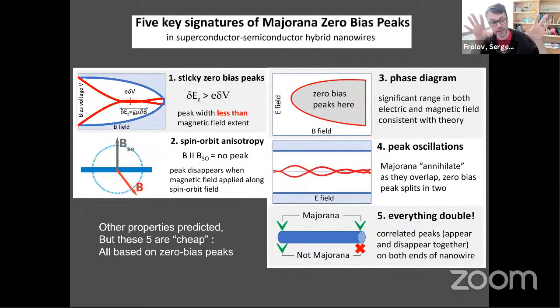So I put together this list of 5 properties, 5 criteria. If you satisfy all 5, there is a great chance you have found Majorana modes in your experiment. And if you're not working with nanowires, but with a different system, there will be your own set of 5, maybe slightly modified, but with some overlap with my list, right? But I showed you that if you look at part of the data, you can fine tune it to look like Majorana, right? So you have to show all 5 in the same device, in the same set of measurements, by the same people at the same university on the same nanowire and so on, right?